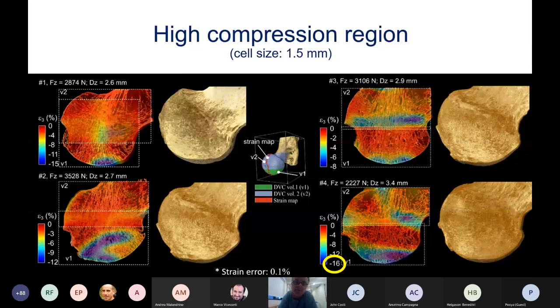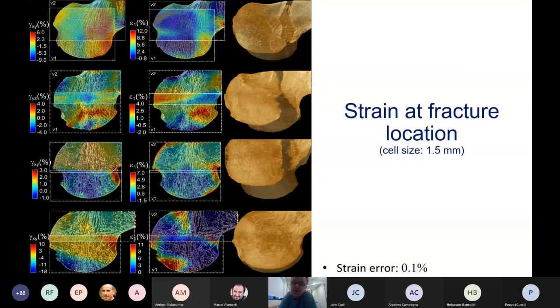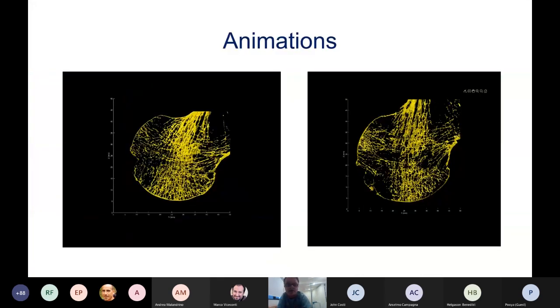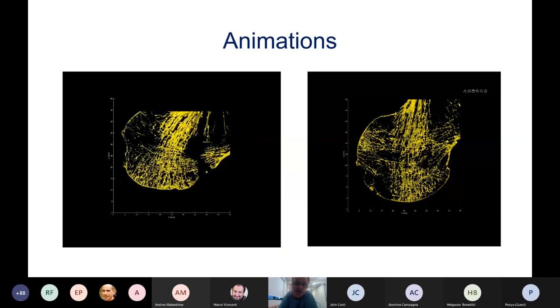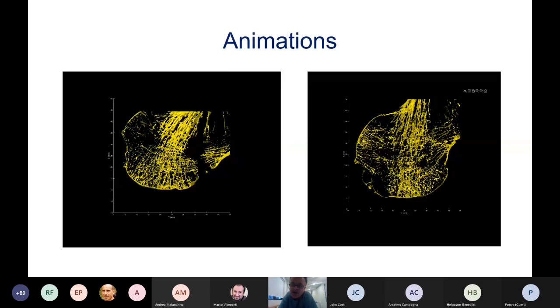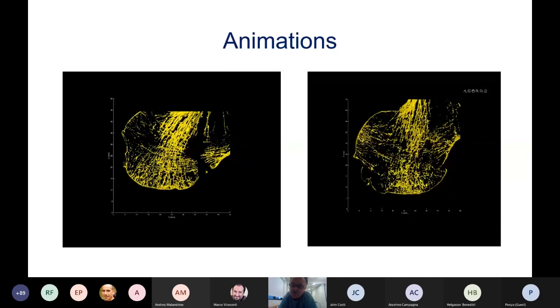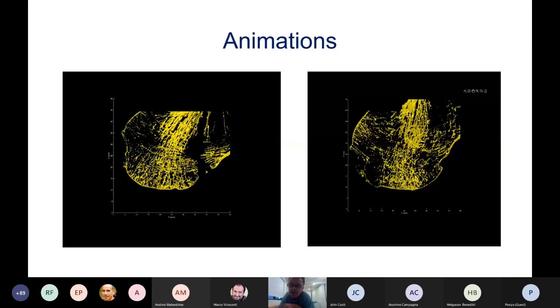If you're looking at what happens in the strain at the fracture location, we see that those locations are displaying high tensile and shear strain. Here we have an animation. On the left is a representative animation of the three specimens that fracture in opening mode, and on the right we have the four specimens that fracture in shear mode.